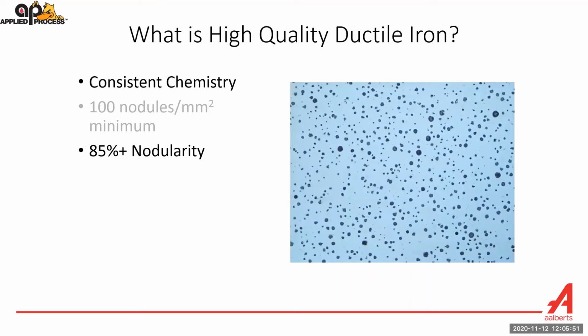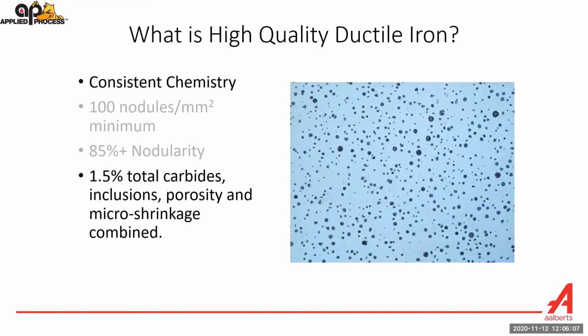And then we want those graphite nodules to be extremely round. Those two attributes help produce good mechanical properties as an end result, and also help us aust-temper the material to get better mechanical properties. And of course, you don't want other stuff in the matrix. You don't want carbides, inclusions, porosity, or other things. So good quality ductile iron is important. The wonderful thing is there are many good quality ductile iron foundries in the United States. I'm going to call it, we know where the Rust Belt is. It kind of starts in the Twin Cities, runs through the Oshkosh, Wisconsin area where I live, down through Chicago, Detroit, and then out to the West or the East Coast.